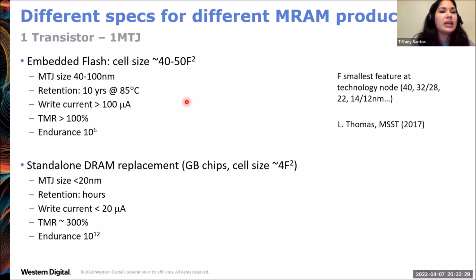For example, embedded flash products that are available now, they typically have magnetic tunnel junction diameter sizes of 40 nanometers and above. Retention, typically the spec for that is 10 years at an elevated operating temperature, write currents above 100 microamps, TMR values above 100%, and endurance about 1 million cycles.